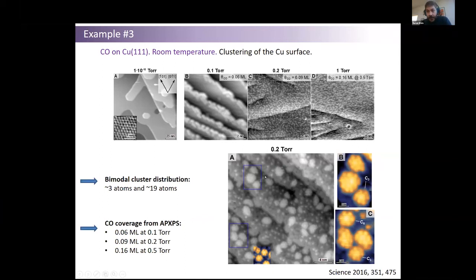These are copper clusters. So the copper surface is broken up into clusters in the form of, well, different 3-atom or 19-atom clusters at this pressure. And you can see actually a 19-atom cluster here, which is 6-fold symmetric, which is a building block of larger clusters. But the importance here is that we show that even the 111 surfaces, which are supposed to be the most stable, can become unstable in the presence of gases.